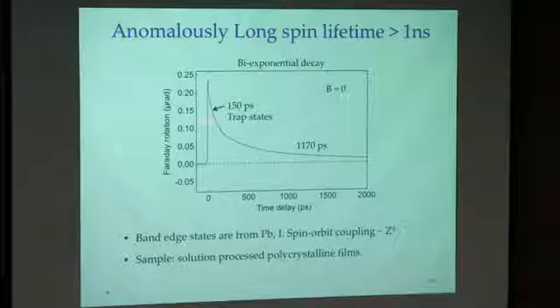Okay, so I would like to claim that this 1 nanosecond is anomalously long for this material, because we know that the band edge states are from lead and iodide, which are really heavy atoms, and spin orbit coupling scales with Z to the power of 4. And the sample, we already saw the SEM image, and we know it's solution processed. It's a polycrystalline film. Considering those facts, we think this is really surprising. And you may also wonder if 1 nanosecond is long or not. The fact that we have seen many oscillations means that within that lifetime, we can do so many operations already. So it is long.